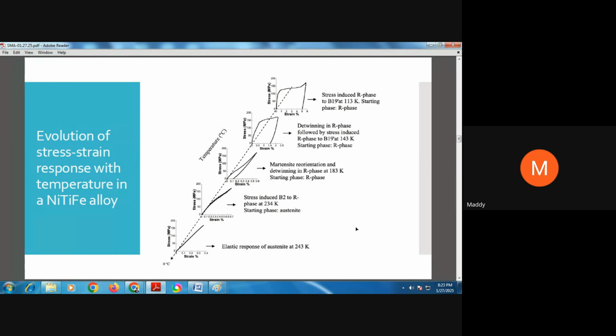Cooling further, where you are still in the R phase, you can see that the martensite reorientation is progressing. You are generating more strain, and you are able to recover all these strains by heating it back to above the austenitic finish temperature. So this is how the material stress-strain response evolves as you start with different phases or a combination of phases. These variations in stress-strain response are used across all the applications that we are going to see. Next slide, please.